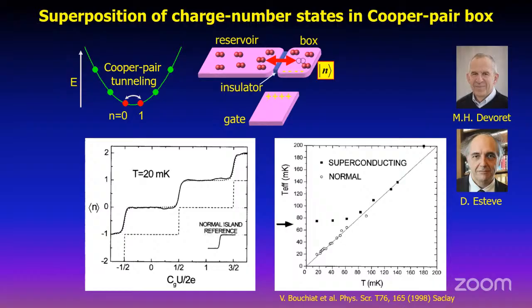So that's what they demonstrated as a function of temperature. At low temperature, obviously, in the case of the superconducting state, this slope fluctuates in contrast to the normal state case. So this is one piece of evidence of the superposition happening between the two charge number states at low temperature.